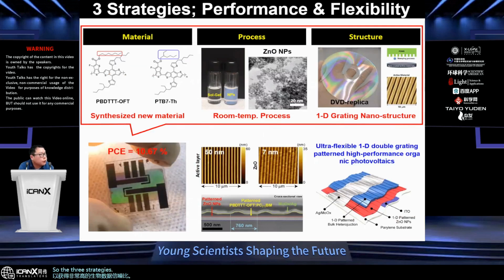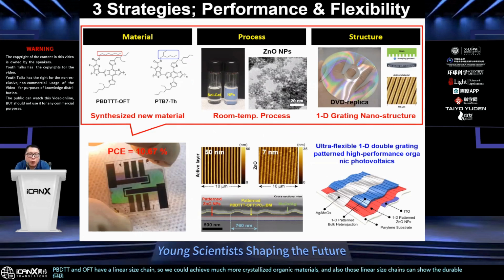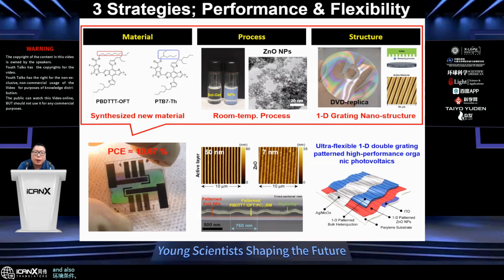Three strategies were applied to achieve highly efficient organic solar cells. The first one is the materials. I normally use PBDTTT-OFT instead of PTB7-Th, which is a very standard material. But PBDTTT-OFT has a linear side chain, so we could achieve much more crystallized organic materials, and those linear side chains also give durable organic layer properties under harsh environmental conditions. Also, by applying zinc oxide nanoparticles instead of a solution-processed sol-gel zinc oxide layer, we could minimize energy-intensive processes, for example the annealing temperature needed to form a high-quality zinc oxide metal oxide layer.